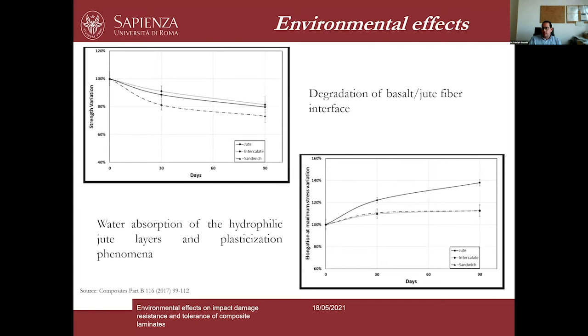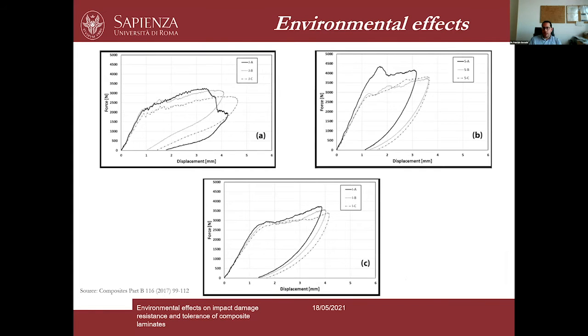How does this actually affect the impact response of these composite materials? Here you see a comparison between the force versus displacement curves after an impact event at the same level of energy, 10 joules in this case, for the three different configurations. In all pictures, the solid curve represents the unaged behavior, and the others the aged behavior after 30 and 90 days. Just looking at these curves, it is pretty clear that there is an effect on the impact response due to the aging. And this is mainly related to the water absorbed by the jute fibers.